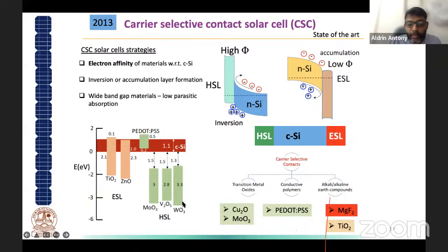So these are the class of materials, that is MoO3, vanadium pentoxide, tungsten oxides. These are the materials which can be used as a hole selective layer, and these are the materials which you can use as an electron selective layer. So these are carrier selective contacts, transition metal oxides, the materials which are between group elements 3 to 12, and especially copper oxide, molybdenum oxide, and magnesium. And titanium dioxide and zinc oxide are the materials used as electron selective contacts.